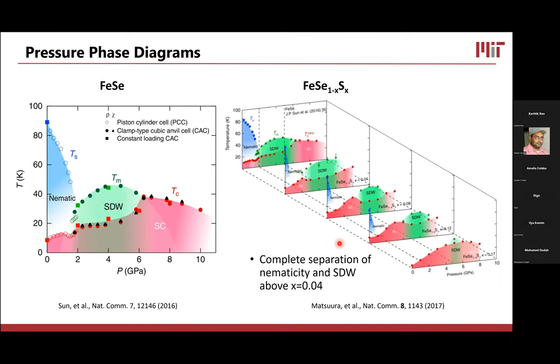But what's really interesting to me here is that as you go up in pressure at these different dopings, this first order transition between the nematic and the spin density wave phases separates. So before they crashed into each other with no doping, out here at middle doping and higher, you see that they actually occupy separate pieces of the phase diagram. So that further complicates the idea that this spin density wave phase is tightly connected to this ambient pressure nematic phase.